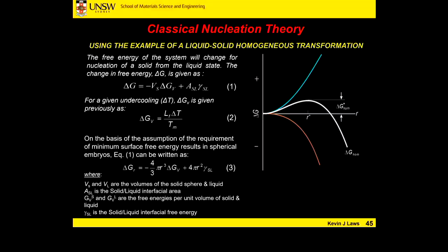Right. So we've got this trade-off between volume and surface area as this thing's trying to grow. And that's what we were seeing in that movie, those stochastic events of that solid phase trying to grow, and then it's getting pulled back, and it's trying to grow over here and getting pulled back, very close to the melting point. And not until we had two regions there that were able to form a larger volume were we able to overcome this interfacial free energy to let it grow.